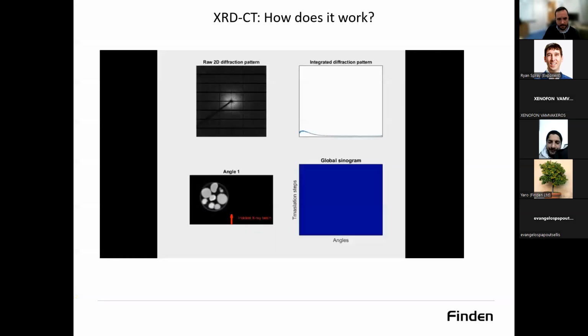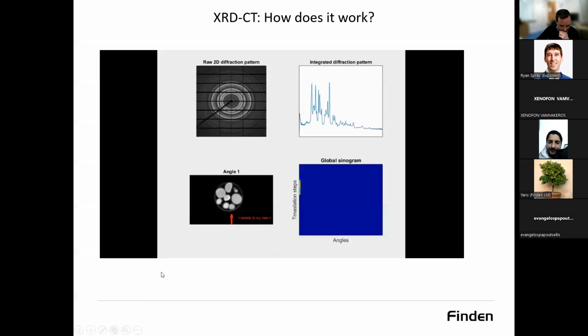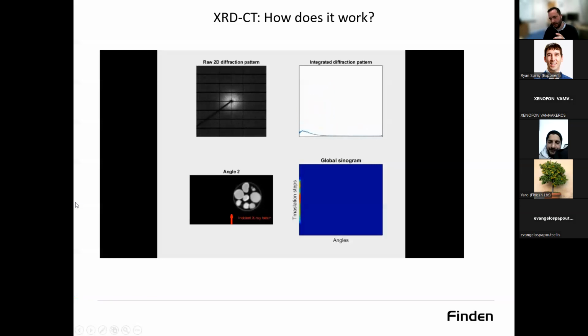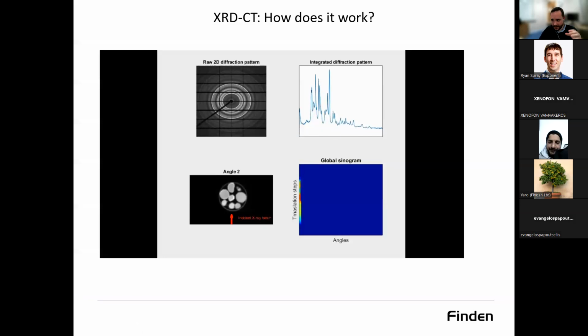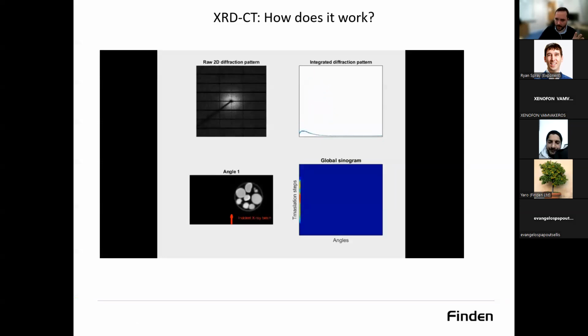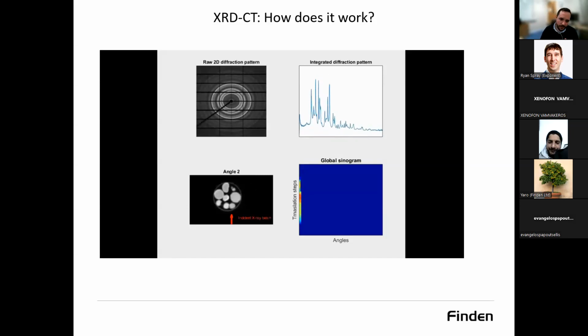I have a little animation here, hopefully it will play. Yep. So you translate your sample across the X-ray beam, and at each translation step, you collect a 2D diffraction pattern. At the end of this line scan, you rotate your sample to the next tomographic angle, and you repeat this process until you cover the 0 to 180 degrees angular range.